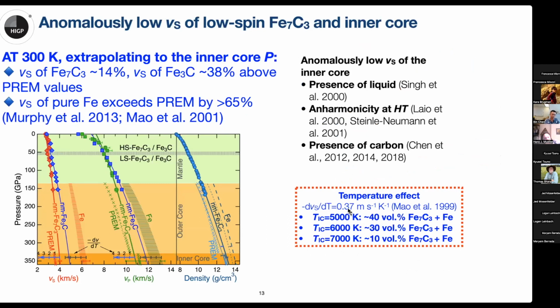So we observed, by extrapolating our data to the inner core pressure, that our Vs of both iron carbide phases are closer to the PREM values. If you look at the Vs of pure iron, it exceeded the PREM value by more than 65%, but our values are closer. If we consider the temperature effect and the range of the inner core pressure, we could estimate the volume percentage of iron carbide phase in the Earth's inner core.